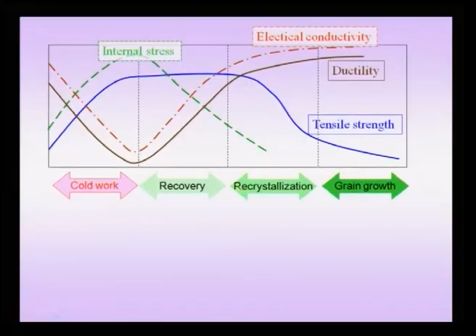During recrystallization, we have noted that there is a large change to the dislocation density, there are new strain free grains which may form, and that means that overall my entire microstructure is somehow refreshed. During grain growth, these strain free grains continue to grow, that means the overall grain size increases, and this further can lead to a change in the properties. So let us see how some of these properties, and here we are talking about properties like electrical conductivity, ductility and tensile strength, and all these of course are a function of the internal stress, the internal stress being in the form of dislocation density, etc.